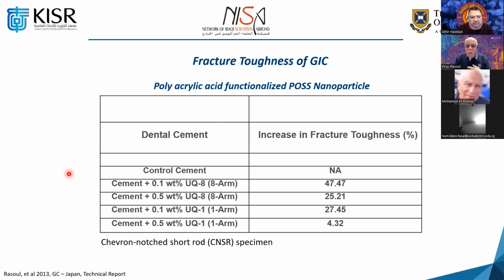Looking into some results, which we did, we saw very, very nice results, particularly when we use a small amount of this material in combination with the other acrylic acid and itaconic acid. You see almost 48% improvement in fracture toughness. So this type of material can be used for application in the molar, which is the back teeth, rather than only the front teeth. And of course, this work has been funded by the Japanese company, the GC company.